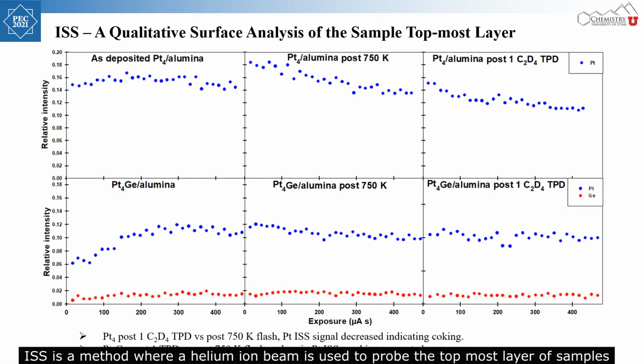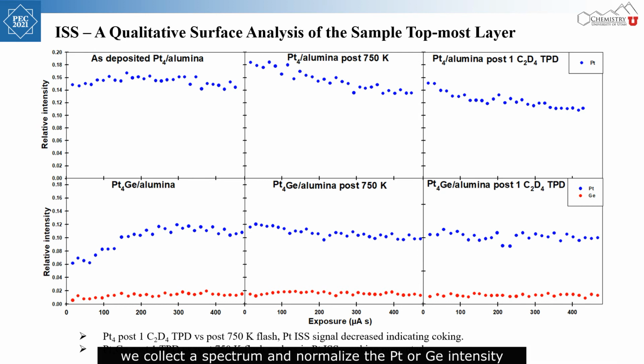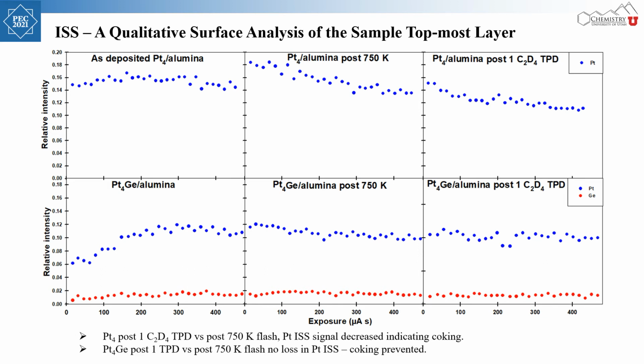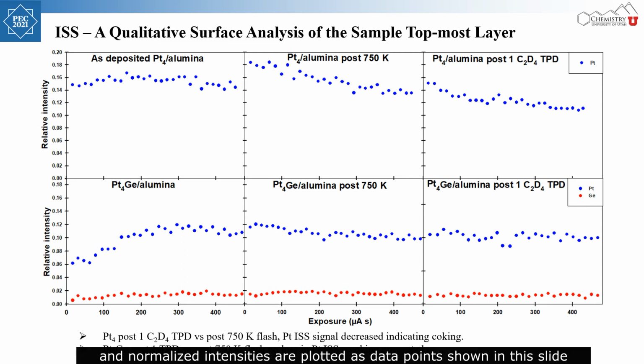ISS is a method where a helium ion beam is used to probe the topmost layer of samples. We collect a spectrum and normalize the platinum or germanium intensity by dividing it by the total amount of helium scattered signals. Multiple spectra are collected over a time period of 20 minutes, and normalized intensities are plotted as data points shown in this slide.